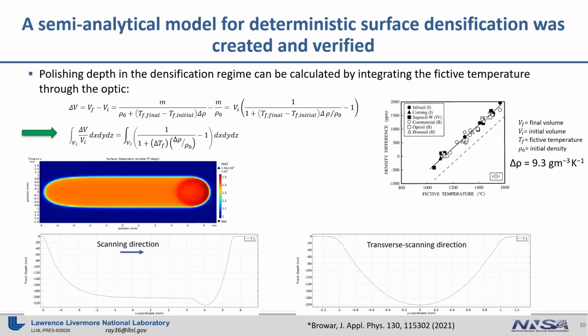And so from the fictive temperature, I mentioned that we can get the polishing depth and residual stress. And so I'm not going to walk us through all of the math, but where you see the green arrow on the right-hand side of that equality, basically that's an expression that we can integrate. And so from the plot on the right side of the screen, it's the empirical relationship, how the density changes with the fictive temperature. So knowing that empirical relationship and the fictive temperature that the model outputs, we can predict what the polishing depth will be. So on the bottom row is the polishing depth.